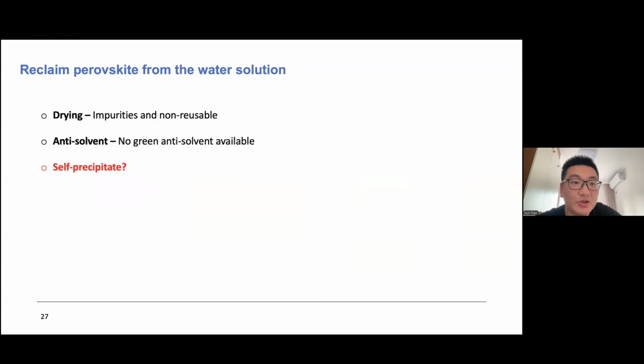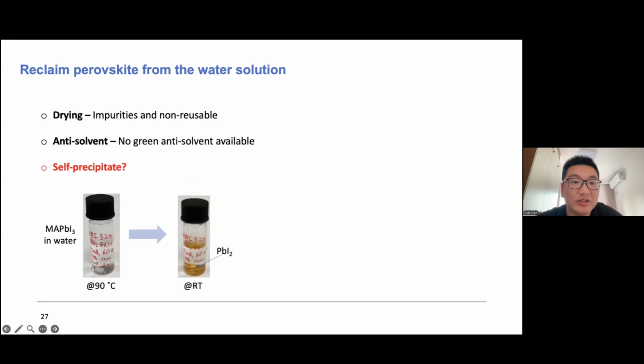We actually tried the drying process before. That means we just evaporate the solvent and get the perovskite powders out, but we found this can introduce more impurities because we add so many ions, the sodium ions, the acetate ions, and also the reductant. And this drying process will make the recycling process non-reusable. That means we cannot use this solution for another recycling.